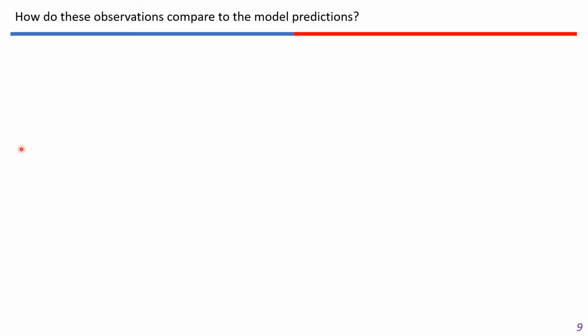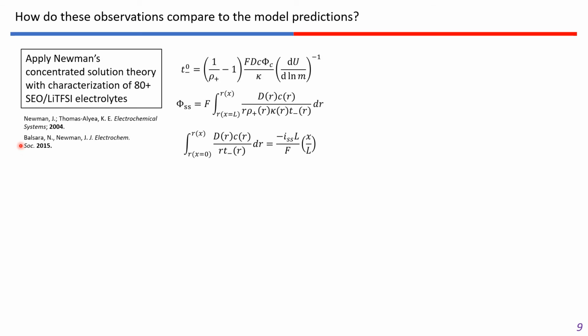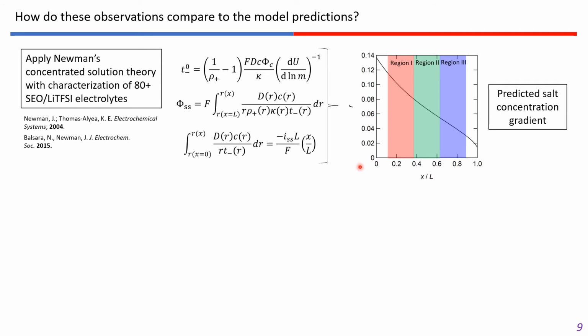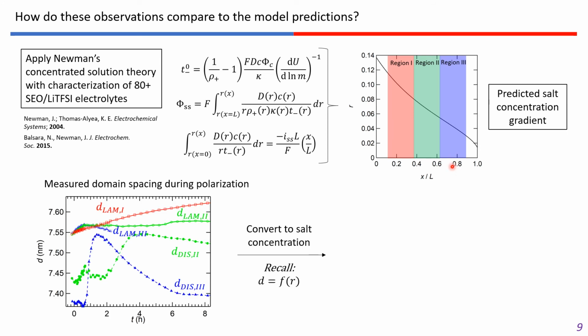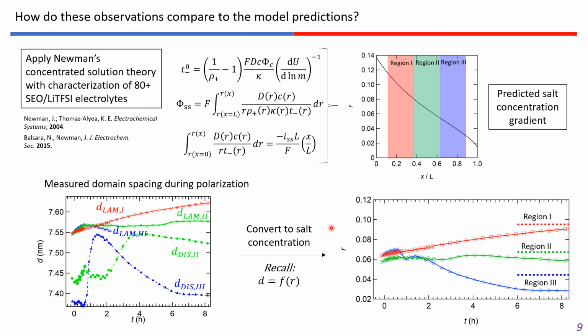So the next question we want to ask is how these observations compare to the model predictions. As we mentioned, we can use Newman's concentrated solution theory and these equations, along with our measurements of the different transport parameters as a function of salt concentration, to obtain predictions of the local salt concentration as a function of position in the cell, and then obtain average salt concentrations for each region at steady state at the end of polarization. We can then go back and look at our SAXS data and pull out domain spacings as a function of time for the various positions, and then, I won't go into the details, but we can use our fits to convert these domain spacing measurements to salt concentration.